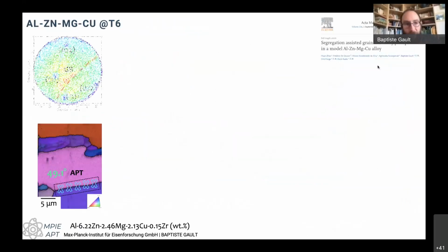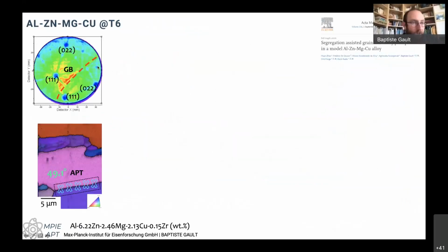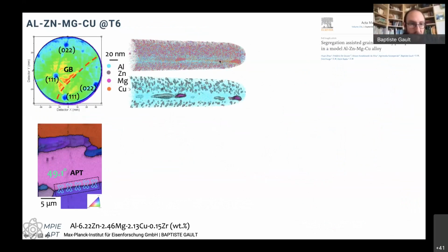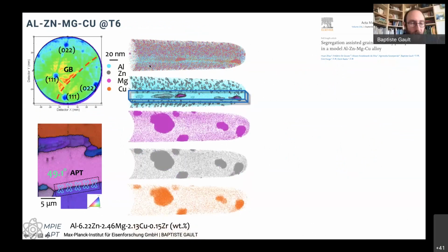But if I get back to some of this aluminum data, so that's the maps I've shown you before with this short movie, I can see that this is the grain boundary that I've analyzed. So I've crossed into it, and then it's going straight down the data set afterwards. And I can go down to, again, looking at how the atoms are arranged within the grain boundary, how these precipitates are arranged with respect to each other, what is their composition.